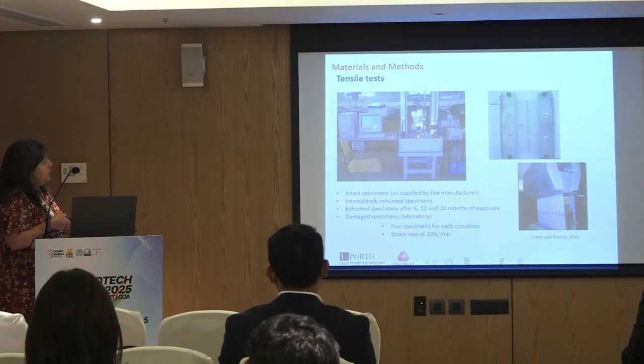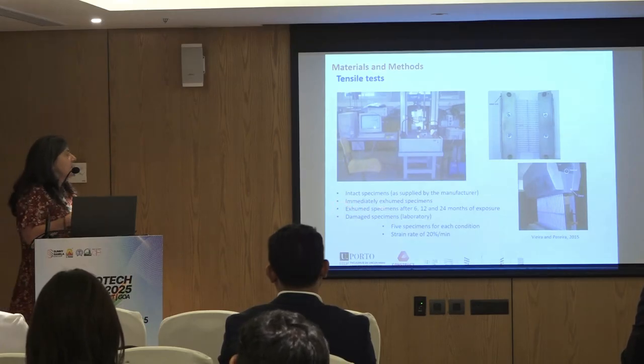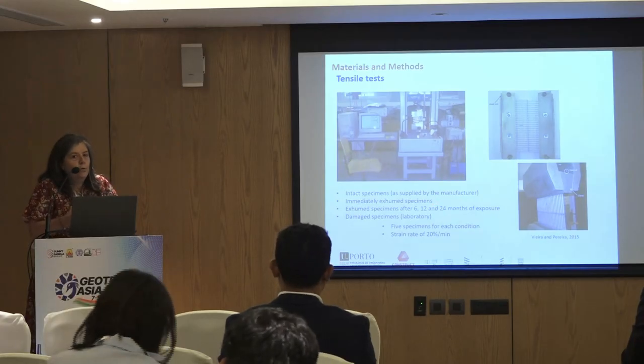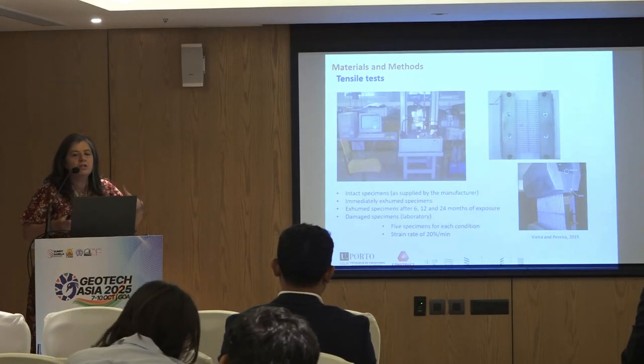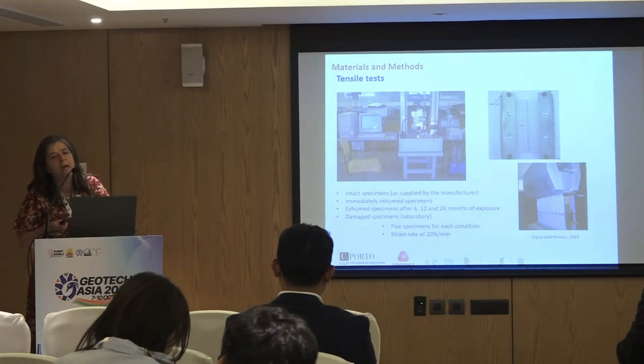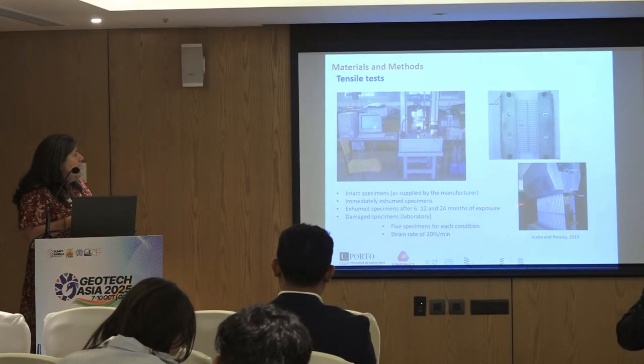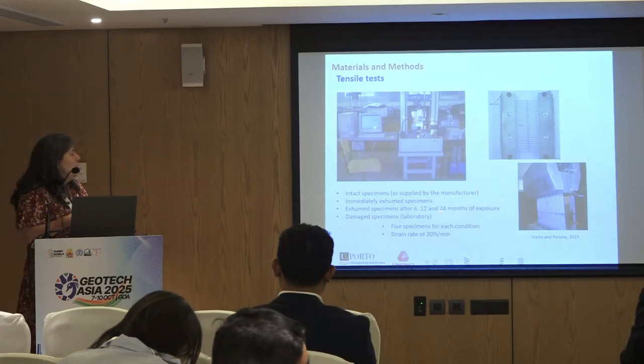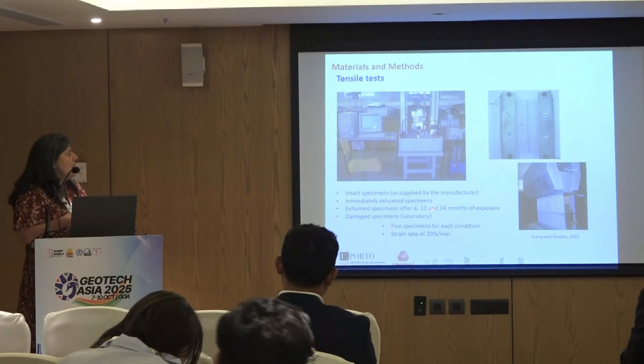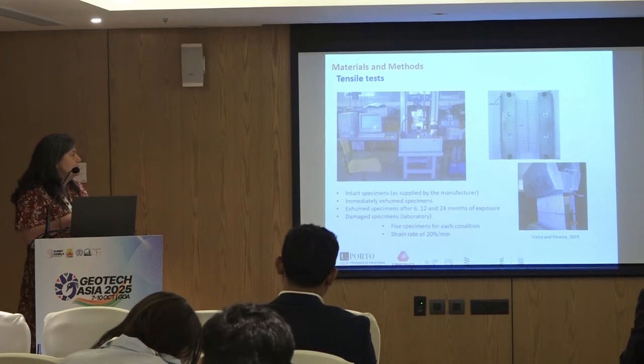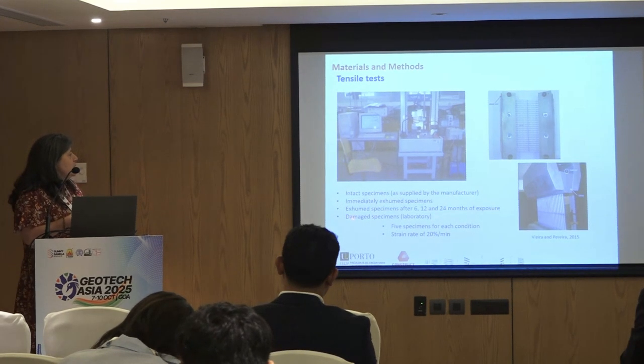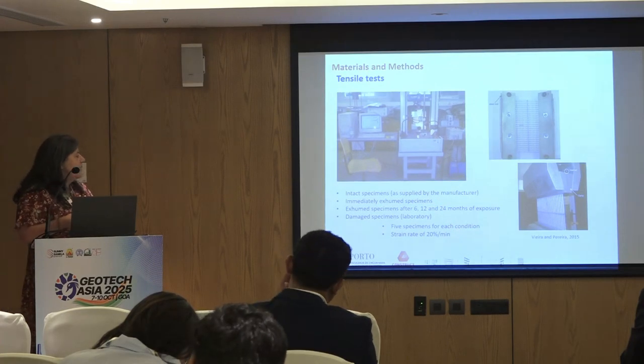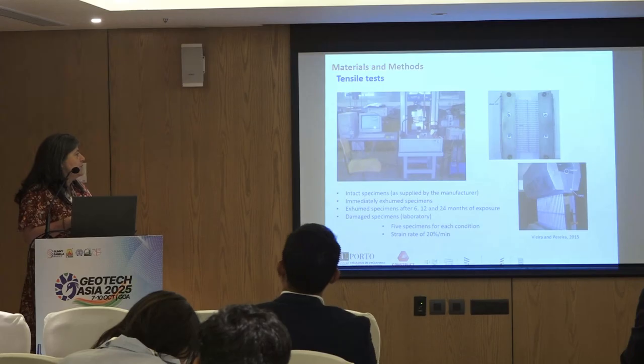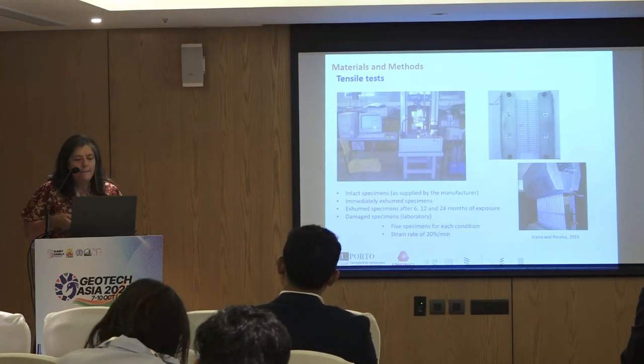We also performed tensile tests on immediately exhumed specimens to isolate the effect of the construction of the embankment from that of the exposure to the fill materials. Tensile tests on specimens exhumed after 6, 12, and 24 months of exposure were also carried out, and also for specimens damaged in the laboratory. For each condition, 5 specimens were tested, and the tensile tests were carried out at a strain rate of 20% per minute.